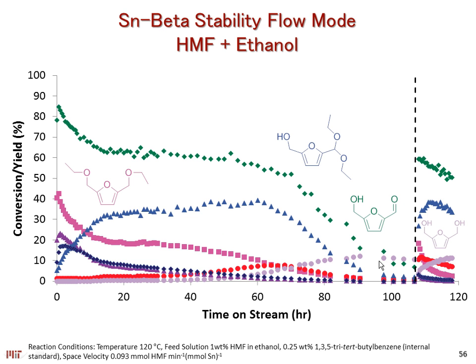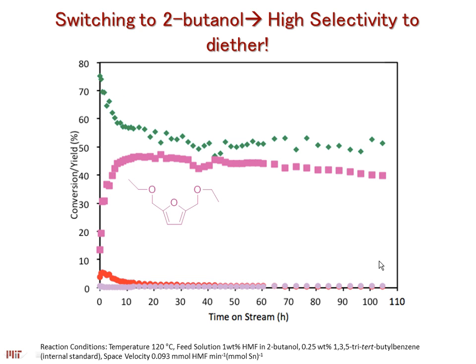Now, when we switch to, for example, 2-butanol as the alcohol, suddenly we see almost quantitative yields of our diether over long periods of time, in this case with our tin beta. For example, you see this initial deactivation followed by a steady state conversion over here where we don't see any acetal products and we see almost exclusively the diether product. And this is something that we're trying to investigate. What is the difference when we do this etherification with ethanol versus butanol?